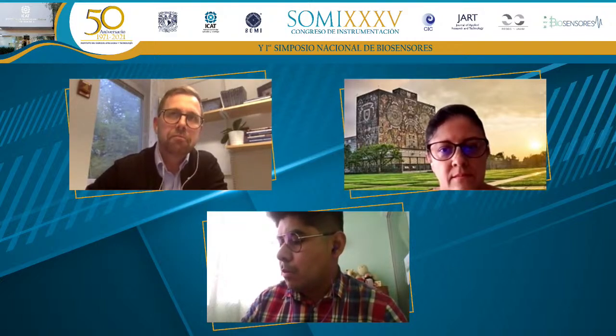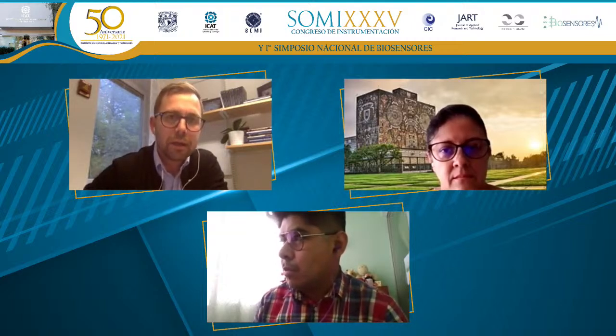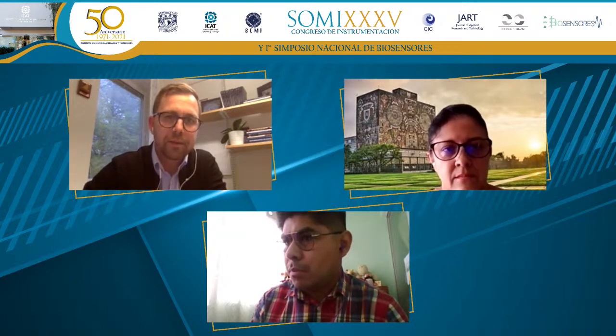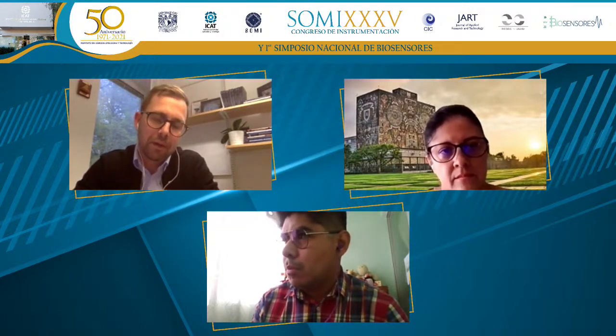It can influence sensitivity, at least when using this kind of fiber optical detector that we use, because we need to collect the scattered or reflected photons. With the setup that we use, that's a limitation, so we can't really go much smaller. But in essence, you're not limited in size. Essentially, you can do refractometric sensing on a single nanoparticle using dark field microscopy. So we can go tiny if needed.